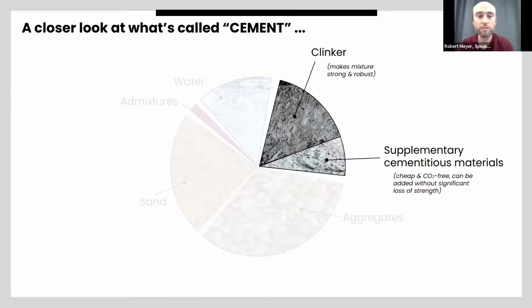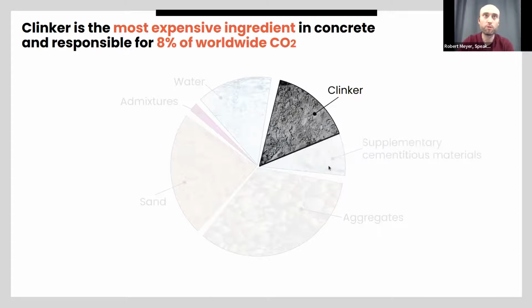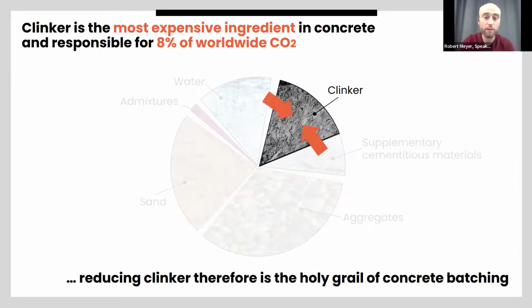We are mostly interested in something called limestone flour, or just fine limestone, which is limestone that has been ground very, very finely without burning it, meaning there was no CO2 released, and therefore it doesn't have a CO2 footprint. So now the idea is very straightforward. Just replace the clinker with CO2-free filler material. That's what we want to do. Just reduce the clinker in this entire mixture.